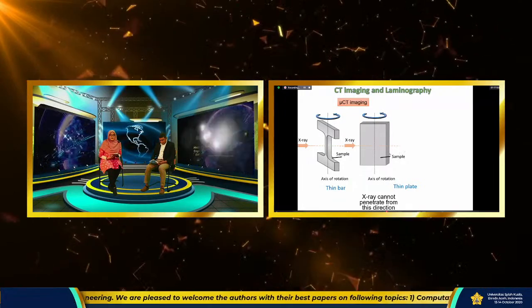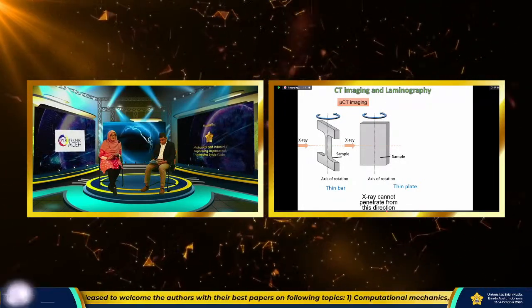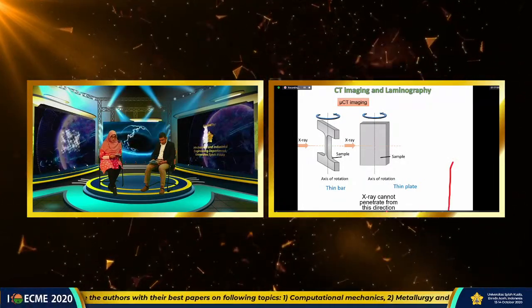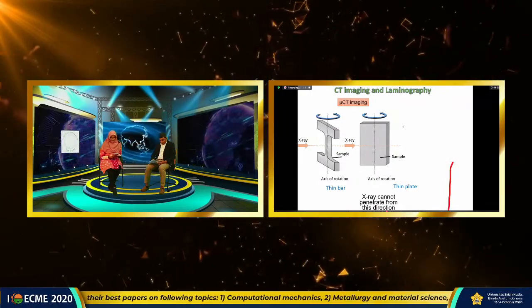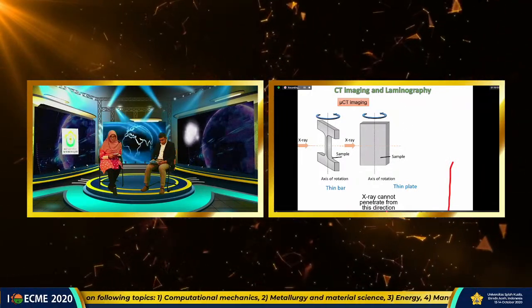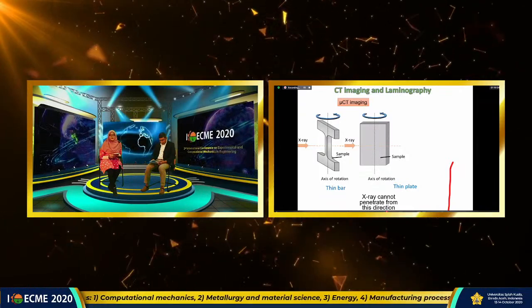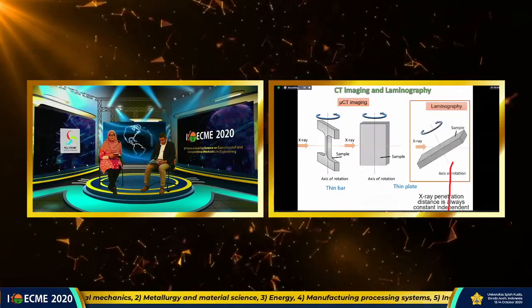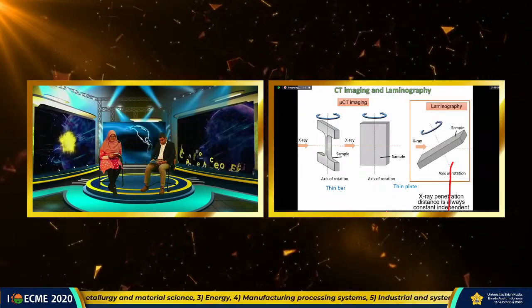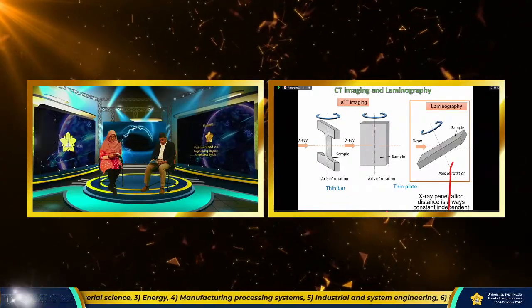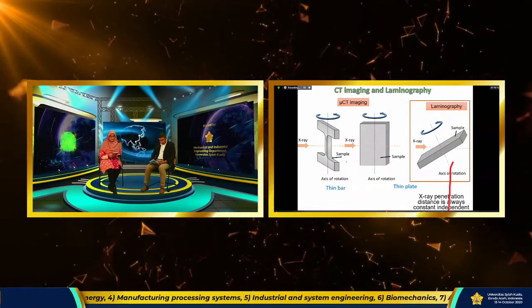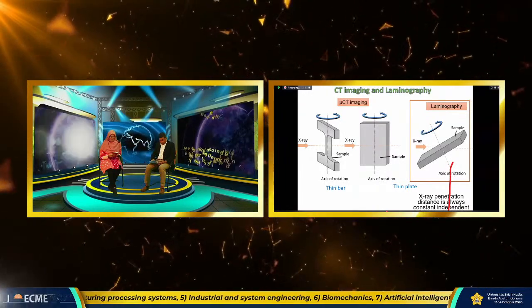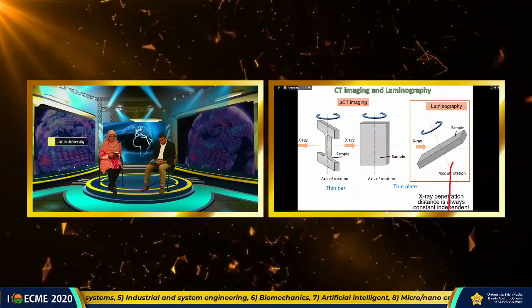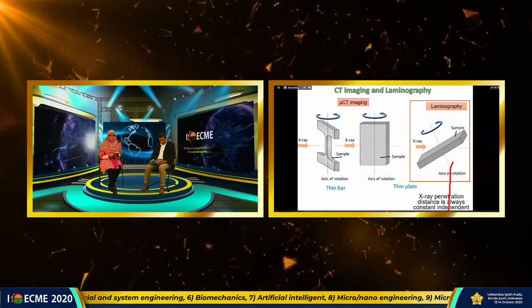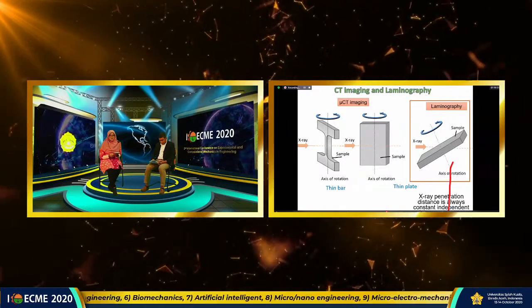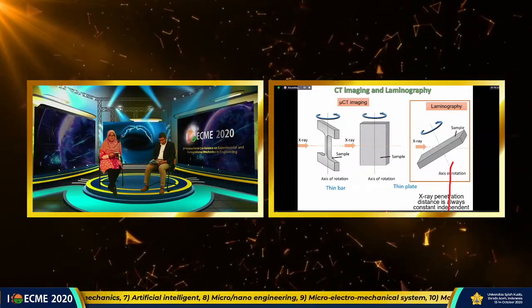So, for normal CT imaging, we cannot control this. But if you tilt the rotation axis like this, the X-ray penetration depth is always constant, so we can construct the image of a thin plate. This is called laminography.